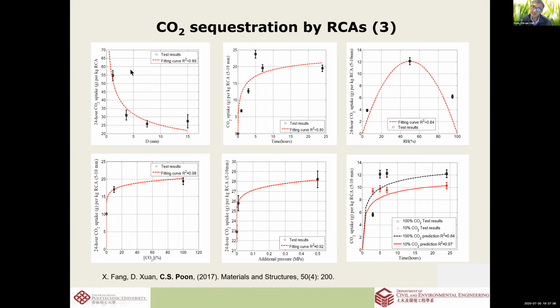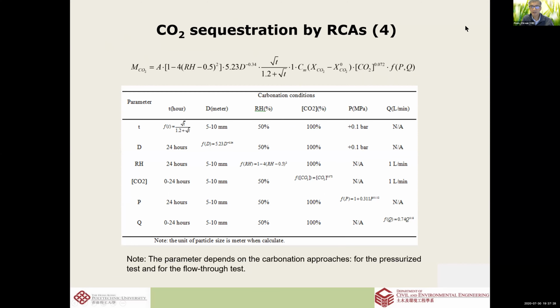So after this, we provide some empirical model for predicting the carbonation, given the particle size and given the CO2 concentration, we can predict the carbonation efficiency of certain processes, and this would be helpful for industrial processes. So these are the empirical formulas that we developed, and also there are some empirical constants that relate carbonation efficiency to different parameters like RH and CO2 concentration, for example.